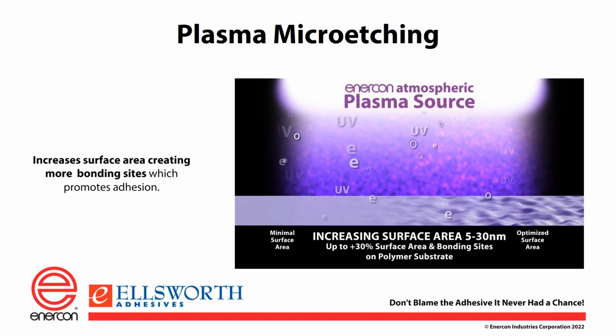The second thing it does is etch the surface. Now this is a micro etch. You can see that we're on the scale of 5 to 30 nanometers. But again, you've got your manufactured surface coming in on the left, going through the plasma stream, and you are etching that surface. Now you can't see this with the naked eye, but we are increasing the bondable area by about 30%. And one of the things that you need to do in order to get a better bond is to increase the area, your surface area, for the adhesives to stick. And so this is the second thing that plasma does to increase the bond strength.